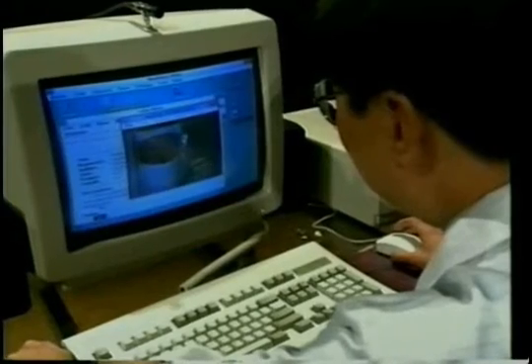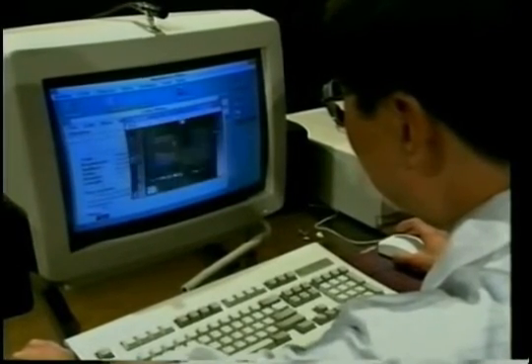Finally, we'd like to remove the glass impregnated Teflon stopper. This is the source of our calcium and magnesium contamination, which we found is a defect problem. And what we'd like to do is replace this with the polytetrafluoroethylene stoppers, which does not contain any filler material. This is our best method for contamination control.